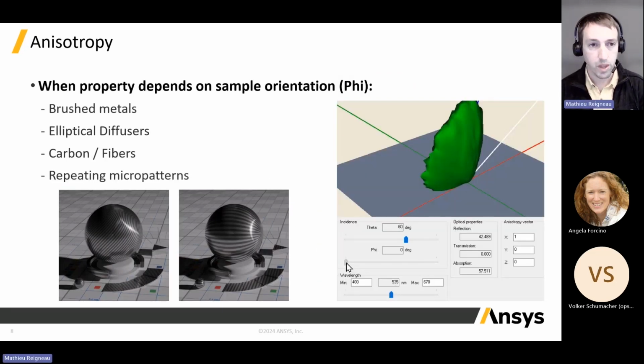Another particularity with anisotropy, which is typically a brush material. Anisotropy depends on the orientation of the material itself. If it's a brush metal, typically, if you light a brush metal with a point light, you will see a straight line appearing, and this straight line will follow the direction of the brush depending on how you orient the material on the geometry. So in Speos, you have the possibility to orient this anisotropy thanks to texture mapping.